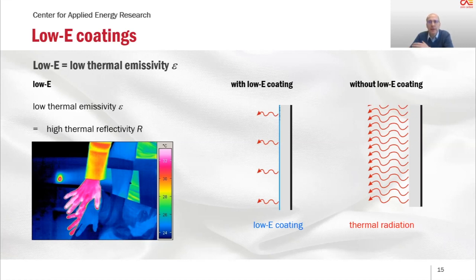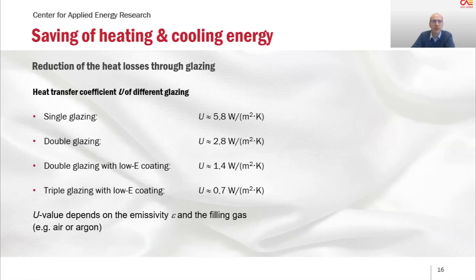In both cases, the thermal insulation is increased by the low E coating, and you can perform some calculations on this topic. For example, here for glazing, by adding low E coatings to glazings, you can reduce the energy consumption by increasing the thermal insulation. And this can lead to a saving of heating as well as of cooling energy. So single glazing, that means a single glass sheet, provides a very poor U value. U value is the heat transfer coefficient. And here you have a U value around 6 watts per square meter Kelvin. This can be halved by adding a second glass sheet. Then you have a double glazing.